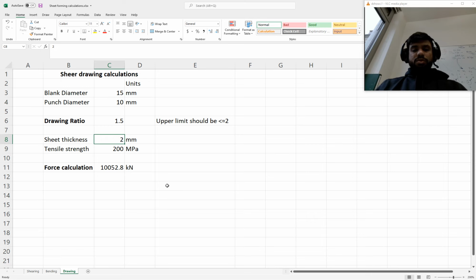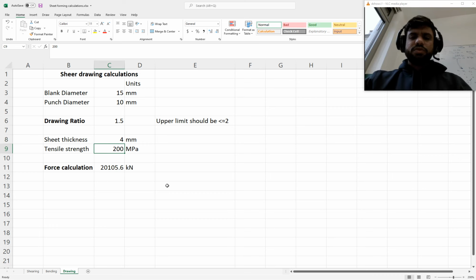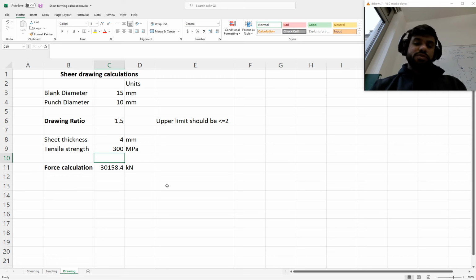And then I want to write here the thickness of the sheet. Let's say the thickness of the sheet is 4 millimeters, and the tensile strength of the material is 300 MPa. Then the force calculation, the total force required is almost 30 meganewtons, which is quite large. But this is a very basic calculation, and it yields these results. We will look into these results later on, how they correspond with the actual experimental values and with the numerical simulation values. But yeah, you can use this sheet for your advantage.